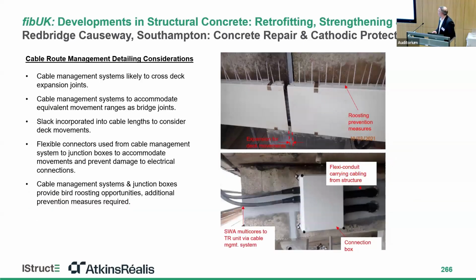Cable tray and connection box. The cable tray we selected was GRP. That removes any long-term corrosion risk. Stainless would have been good, but it's expensive. Galv is always a problem in the long term. And where it crossed expansion joints, we needed to leave a gap in the tray. Otherwise, in the summer, particularly when the bridge expands, you can find on sites where this hasn't been done that the tray starts to bow. It usually goes back again in the winter, but it's something we wanted to avoid on this site.